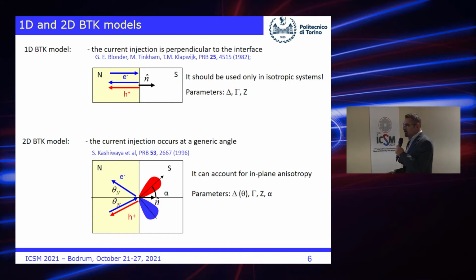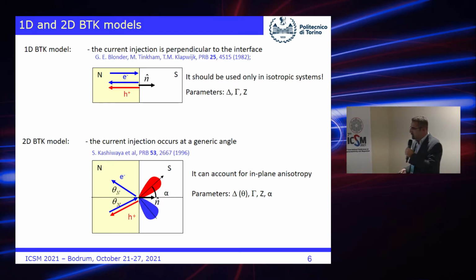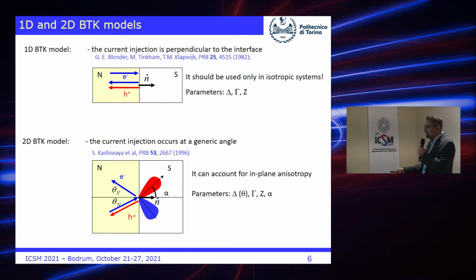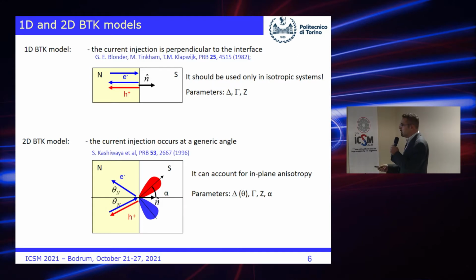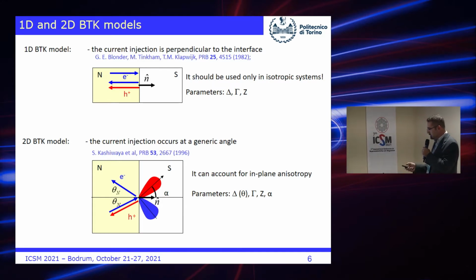Now, the 1D BTK model, the one I mentioned, has the simple drawback that it is one-dimensional, in the sense that the electrons are injected along the direction of the normal to the interface. To account for anisotropies in the order parameters, we have to switch to a more general model that was proposed by Kashiwaya and Tanaka already in 1996, in which we can account for the fact that the superconducting order parameter is anisotropic, because we account for the fact that the electrons can be injected with all the angles with respect to this normal to the interface. Today I will not talk about anisotropic superconductors, because all the ones I measured were in the S plus minus state, so we will anyway use this one because it is more general than this.